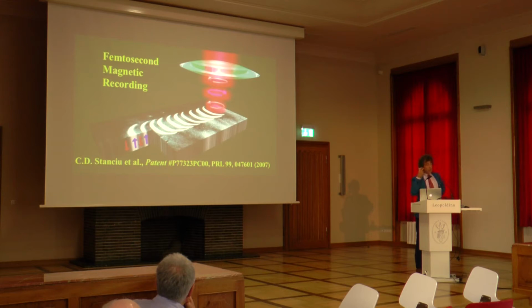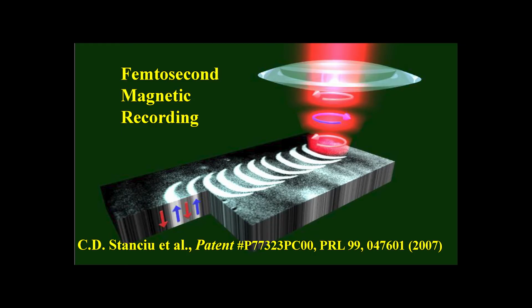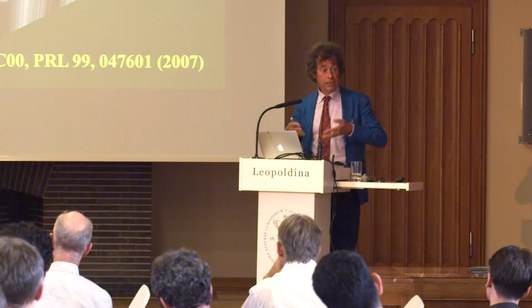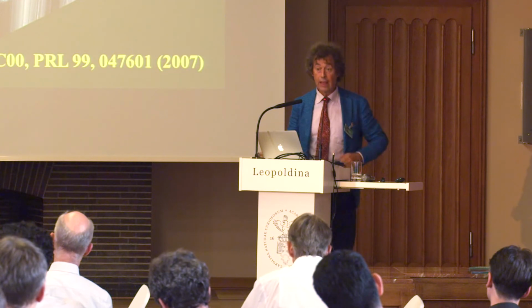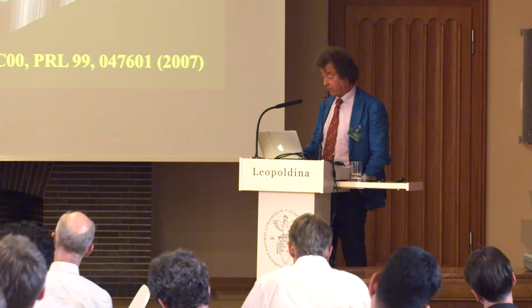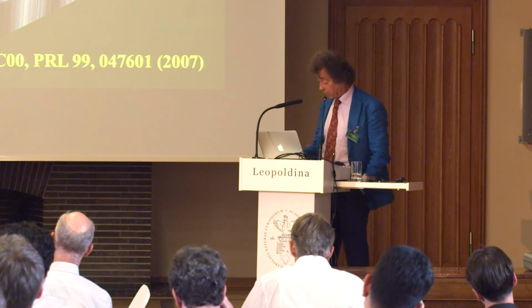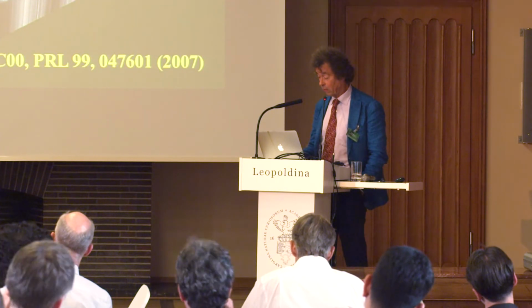Now, in the beginning, that was still on an optical length scale. Then we realized, well, if you really want to do something with that, you have to bring it down to the nanometer length scale. Present day, it's about 50 nanometers, and this was about 20 micron. I will not go into that, but we have done that. We have used plasmonic nano antennas, and we were able to do this whole switching on the 40 nanometer length scale. As a result, we can be competitive with present-day recording.